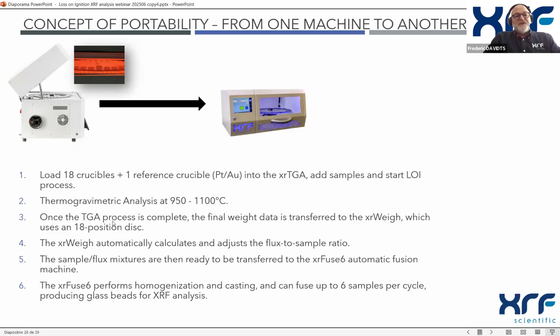And then, when the TGA process is complete, the weights are transferred to the xrWeigh, which also uses an 18-position disk. The xrWeigh will automatically calculate and adjust the flux-to-sample ratio. So the xrWeigh is an automatic machine to load flux. The machine will add the exact flux quantity to each crucible to keep the same ratio for all the samples.